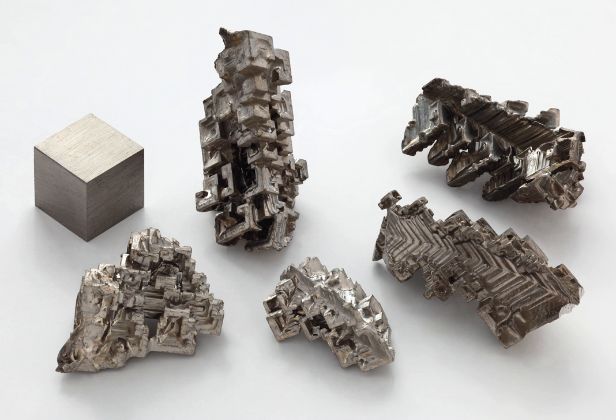Sintering of bismuth and manganese powders at 300 degrees Celsius produces a permanent magnet and magnetostrictive material, which is used in ultrasonic generators and receivers working in the 10 to 100 kHz range and in magnetic memory devices.